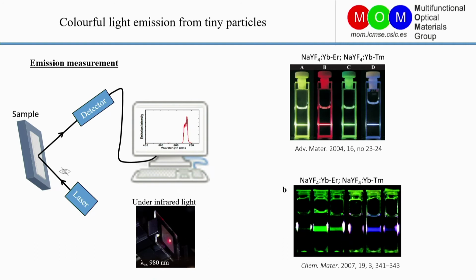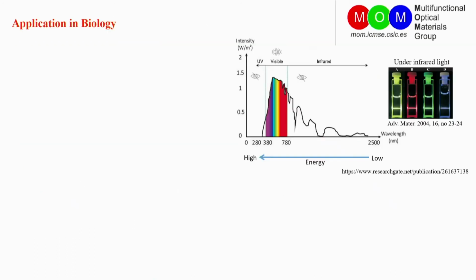Important to note that the particles emit strongly not only in a solid state, but also in a liquid phase. Having high emissions in the liquid phase is one key parameter for the particle to be applied in biology. As mentioned before, the particles can be excited under the illumination of infrared light, which has low energies. The advantage of low excitation energies is less damage to the samples during the measurement. This is another important reason that permits the particle to be applied in biology.